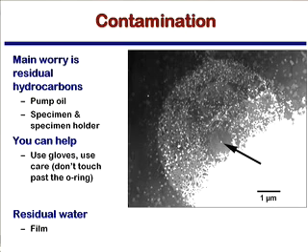So during sample preparation, keep your sample clean. Use gloves when handling stuff that goes into the vacuum. Don't touch past the O-ring in the case of the TEM holder in particular. Use a plasma cleaner if you can. All these things will help you with that. Okay? Okay. So that's what I wanted to say about vacuum.